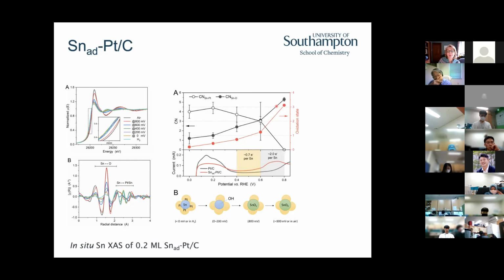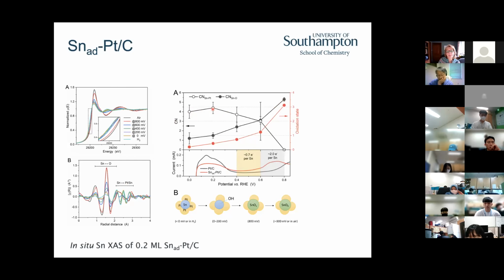If we start from the negative potential, so we're sweeping this way, we can see that the tin has the oxidation states in red. It has mostly platinum neighbors, so we have tin decorating these platinum neighbors. As we increase the potential, we're oxidizing it. We've got OH on the surface. I'm probably talking way too slow, so I'm going to have to speed up a bit here. We have OH on the surface. Eventually, we make a tin oxide.